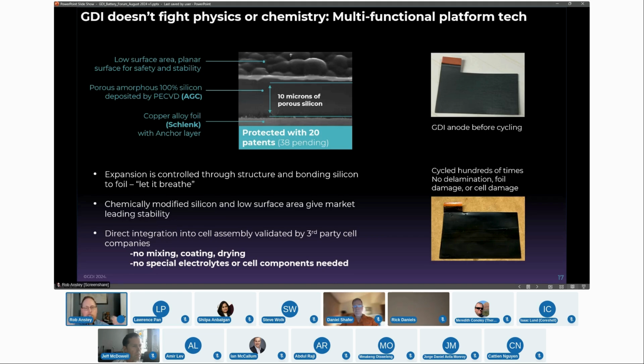And what we did is we took a high tensile strength copper foil that can deal with the expansion of the silicon. We put a patent-protected process, 20 issued patents, 38 pending, to bond a monolithic layer directly to that copper. And that monolithic layer is porous. Silicon's density is normally around 2.2 grams per cc. We took that down a notch to about 1.6 grams per cc, but made it monolithic with low surface area.